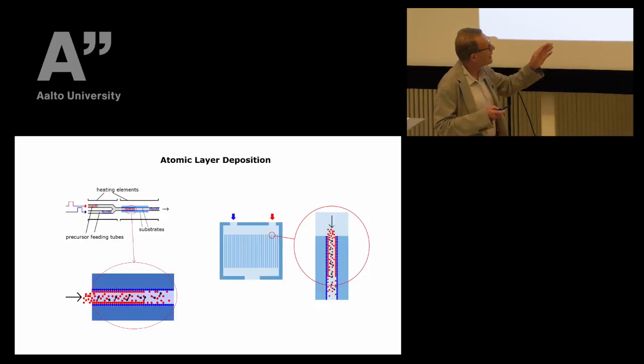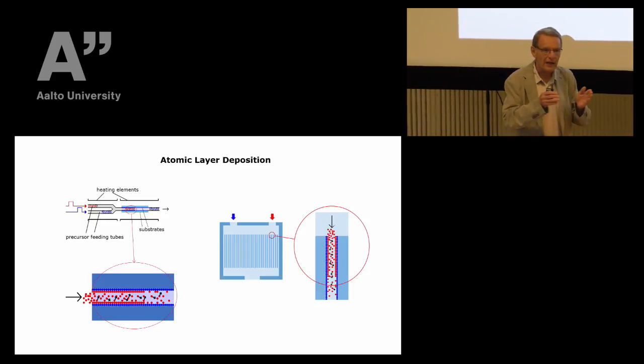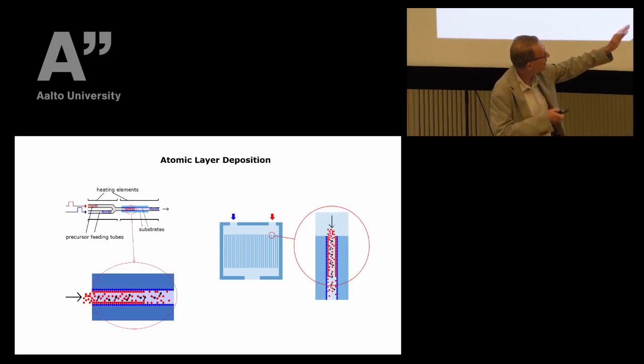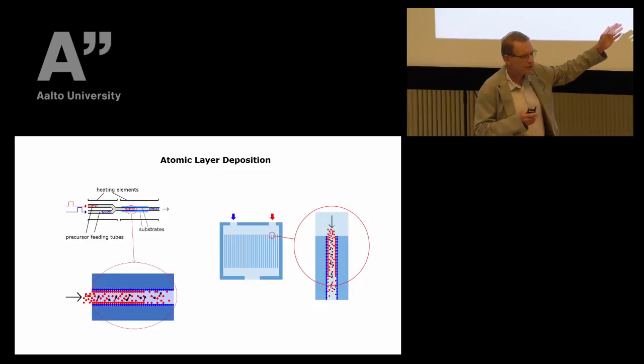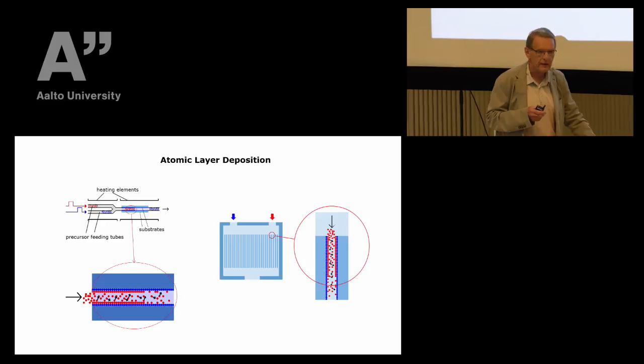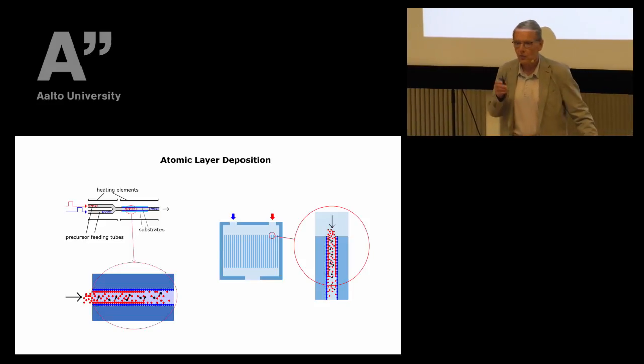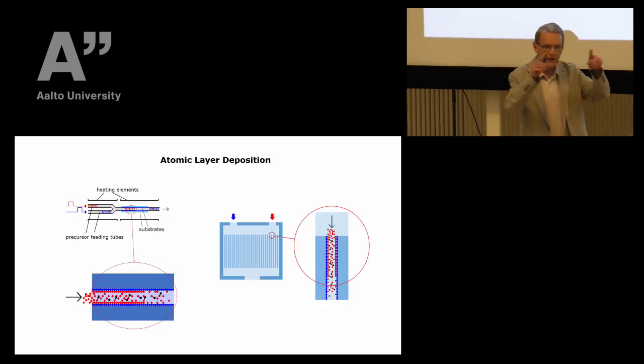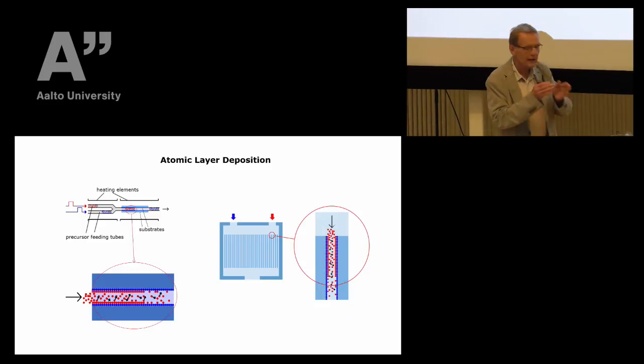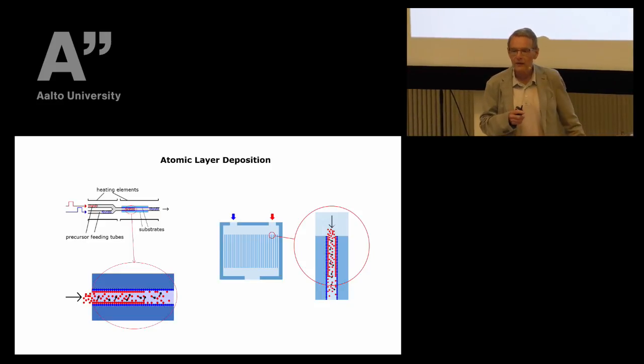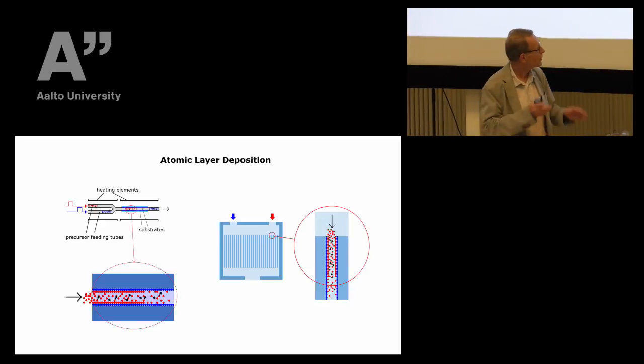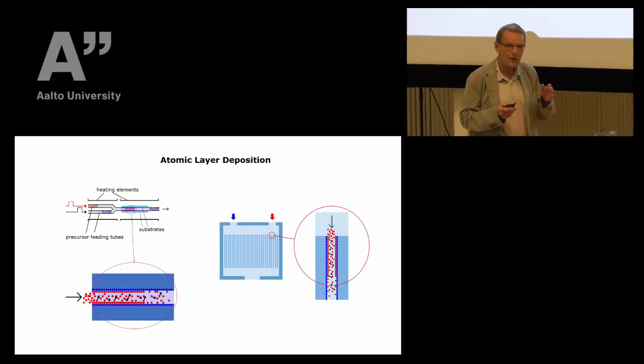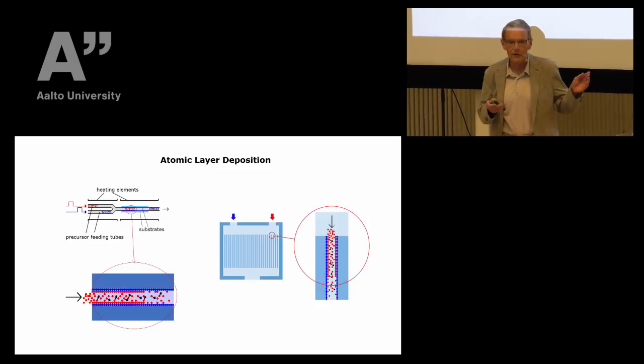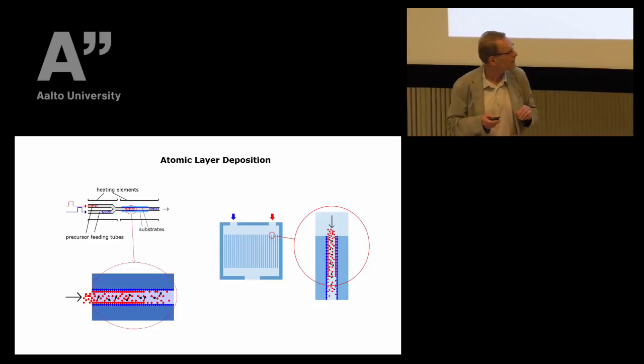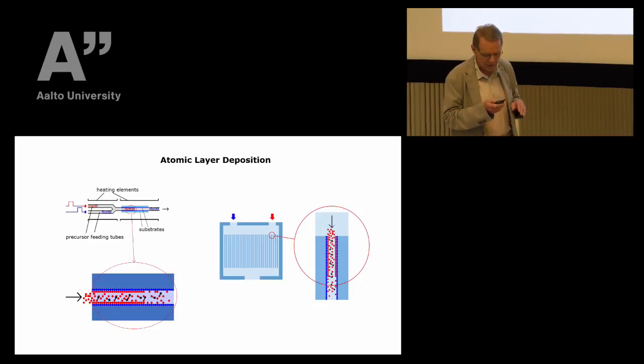Atomic layer. It means that we can compensate the longer time of build up of the material with higher density of substrate. So we can handle many substrates in a very small chamber, and that's the way of guaranteeing the productivity. Because in our applications, which in the early stage was the electroluminescent flat panel displays, the substrate size is very high, and that's why the film thickness, although it's only 1/1000th of a millimeter, in atomic scale means thousands of atomic layers which are needed. So the time is very important here. In modern semiconductors, the layers may be only a few atomic layers for the critical films such as the gate dielectric. So then the time factor is not that important.